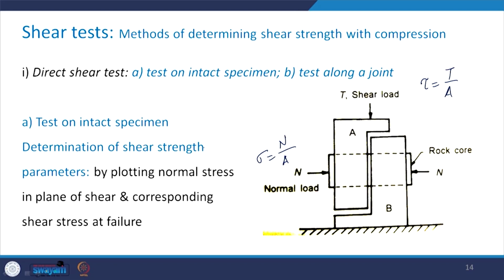If we plot these, here is sigma and here is tau at failure. Let us say I test 3, 4 or 5 specimens and get a curve like this. I can fit a straight line, and assuming that it follows the Mohr-Coulomb failure criterion, I can find the shear strength characteristics by finding this intercept C and this angle phi. So, this is how we can interpret the results from the direct shear test conducted on an intact specimen of rock.